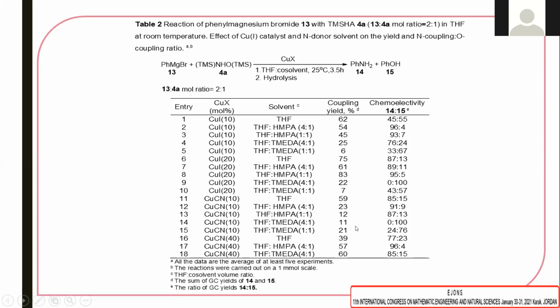Better results were obtained when using 20 mole% copper iodide, both in THF and in THF-HMPA. THF led to 75% yield. We were delighted to find that the reaction in THF-HMPA ratio 1:1 takes place with 83% yield and an aniline to phenol ratio of 95 to 5. These optimized conditions seemed to us an atom-economic alternative to electrophilic amination. The aryl cuprates with N-methylhydroxylamine and TMEDA as a co-solvent gave quite low yields.